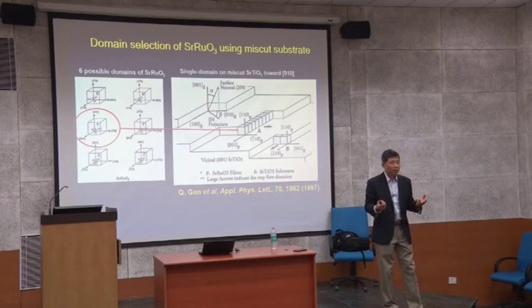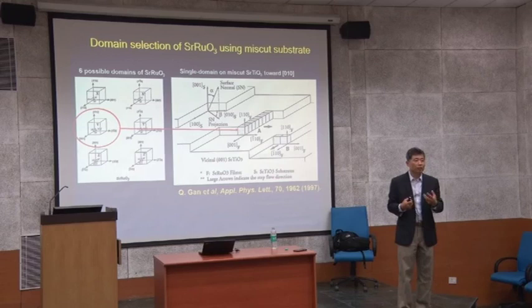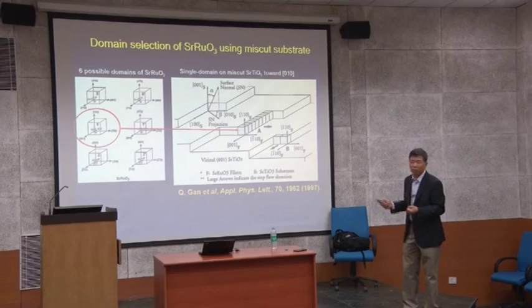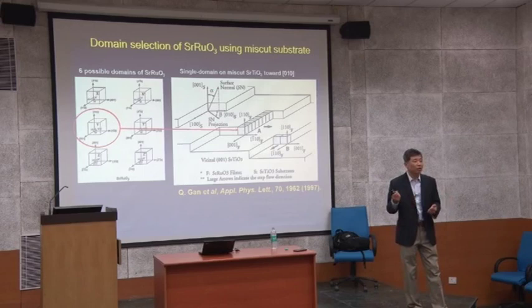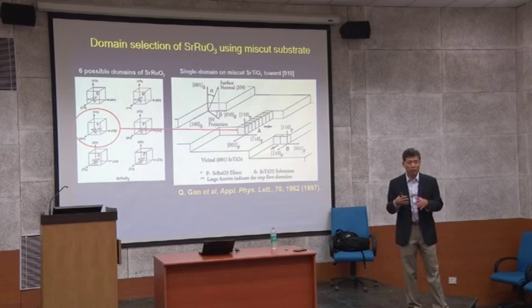But now, because miscut plays a role, you can order the substrate. You say, okay, I need this miscut angle and that miscut direction. You can specify those things. The substrate vendor can measure and provide that variable. And you have to specify the error bar, the variation. Usually they say 4 degrees plus or minus 0.3 degree or 0.5 degree. Or if you ask for 0.01 degree, a much tighter orientation, they charge more. Sometimes you pay more for the labor than for the substrate. For example, for certain two-dimensional electron gas work, you ask for very tight orientation, 0.08 to 0.125 or something.